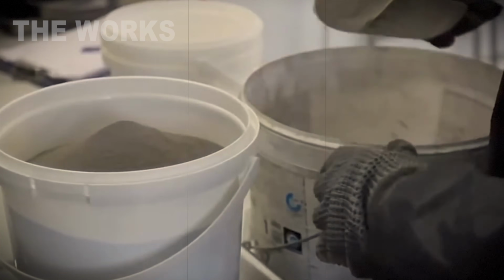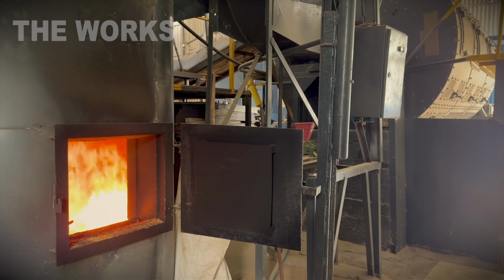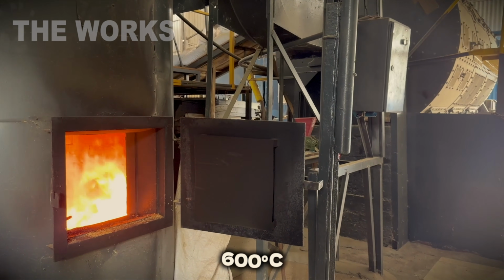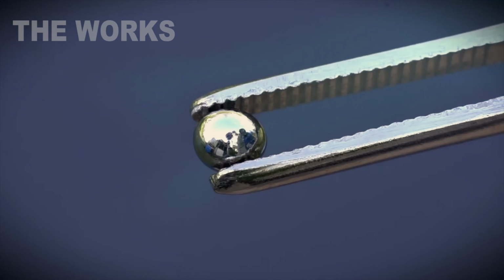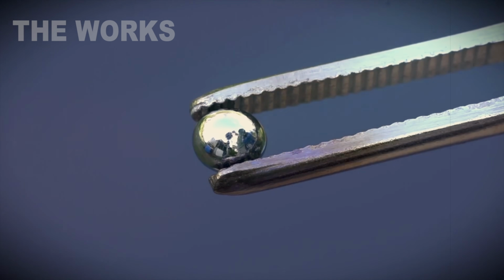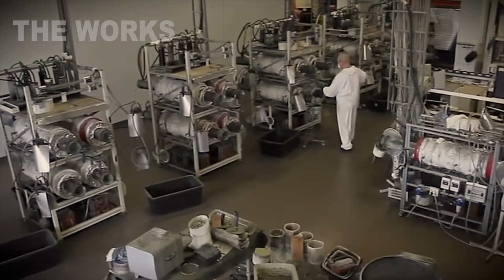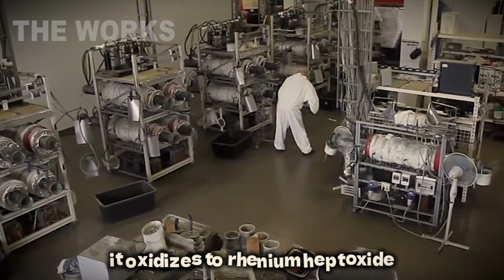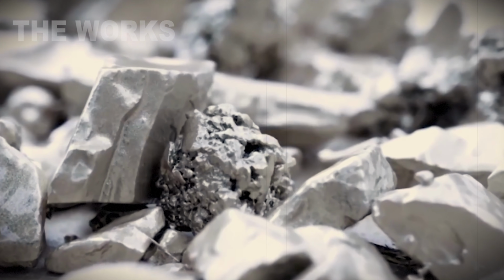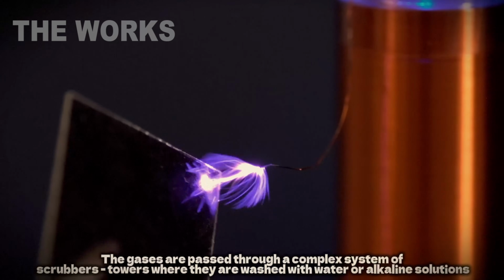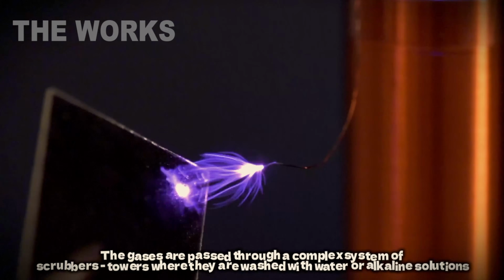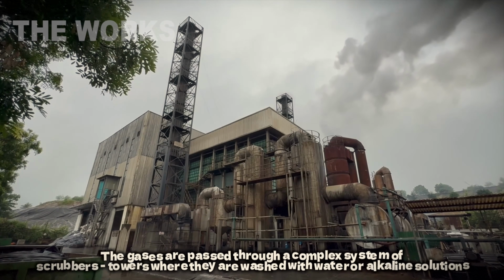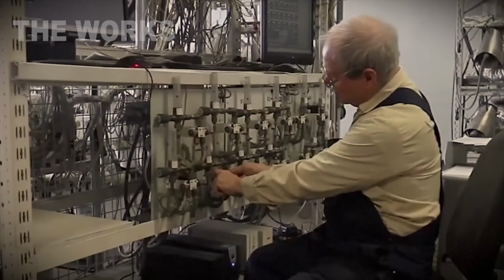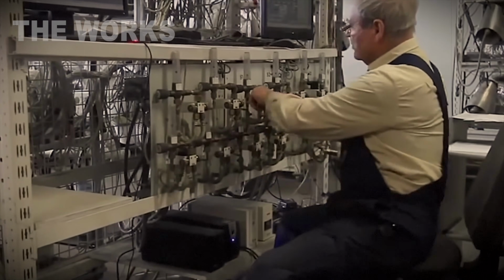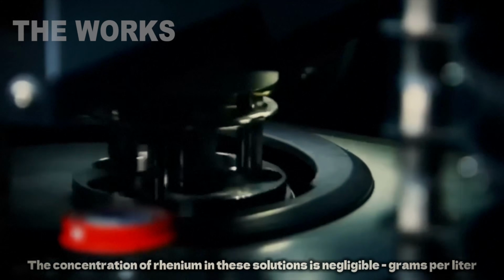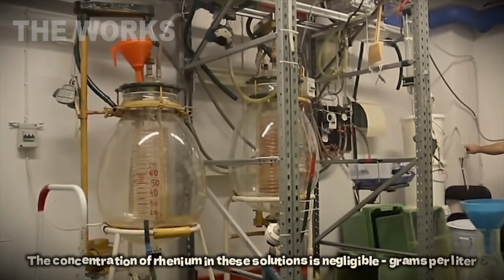The molybdenum concentrate gets roasted in special furnaces at around 1,100 degrees Fahrenheit and higher in open air. Molybdenum oxidizes to trioxide, which can then be reduced back to metal. But rhenium behaves differently. It oxidizes to rhenium heptoxide, which vaporizes at this temperature and escapes with the gases. Those gases pass through a complex system of scrubbers, towers where they're washed with water or alkaline solutions. Rhenium heptoxide dissolves, forming rhenic acid or perrhenates. Rhenium concentration in these solutions is tiny, grams per liter, but that's something you can work with.